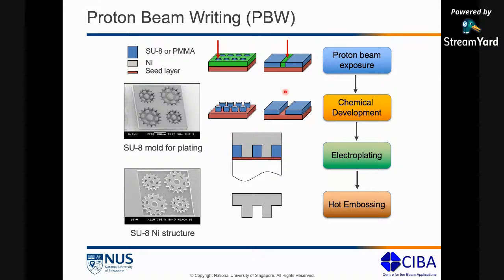We then electroplate this with nickel, and we take away the mold. So what is left behind is a nickel template, which we can then use to replicate the structures by a process called hot embossing. Okay, so the process flow goes like this. It's proton beam exposure to your surface, chemical development, electroplating, and then hot embossing.